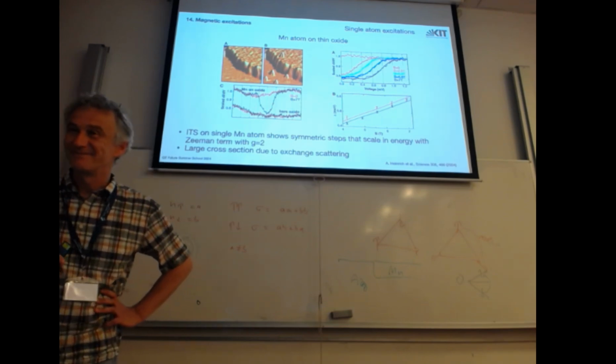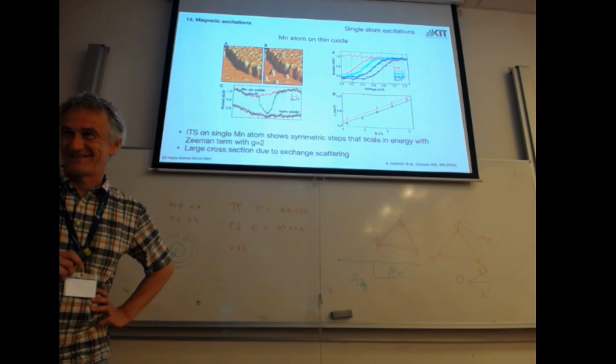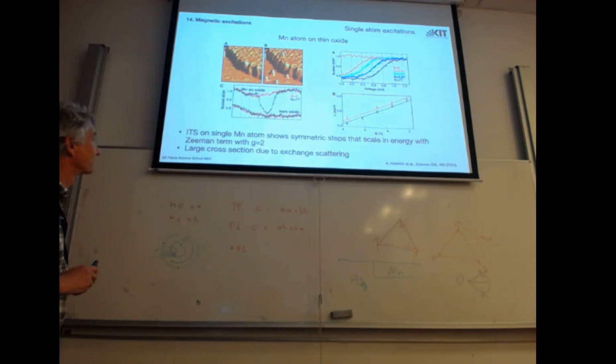I apologize, it was too fast for me. So pictures A and B, do they correspond to magnetically polarized STM, or is it just topography? There's no spin polarization. So what's happening in pictures A and B? A is before manganese, this is after manganese deposition. And now you have this manganese. And now you do tunneling spectroscopy via IV on the oxide, this one, and on the manganese atom on the oxide, these two. This is for B equals 0, and this is for B equals 7.